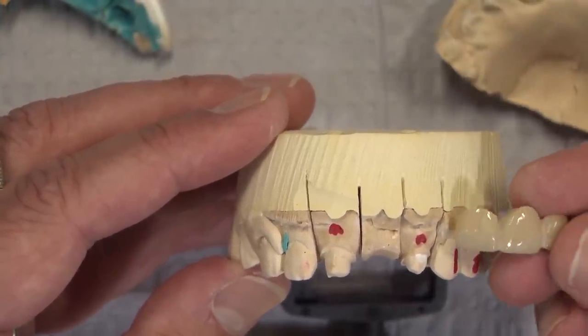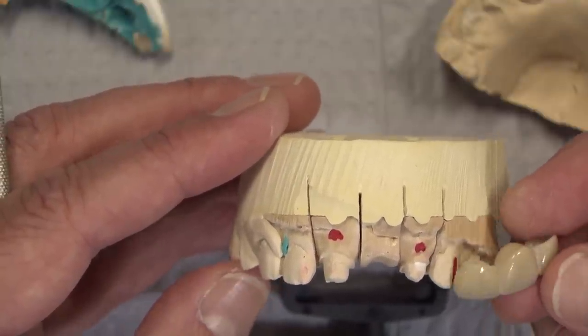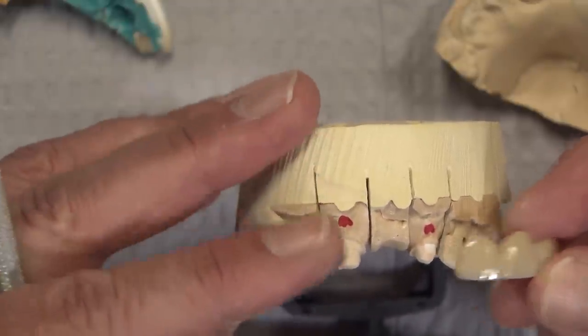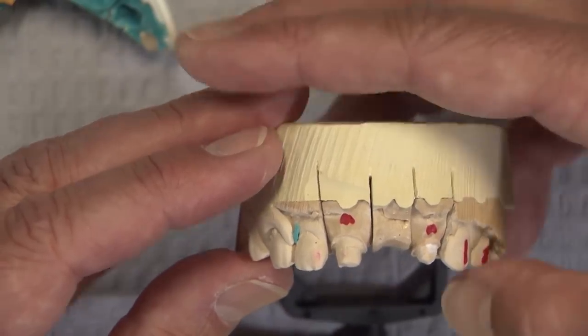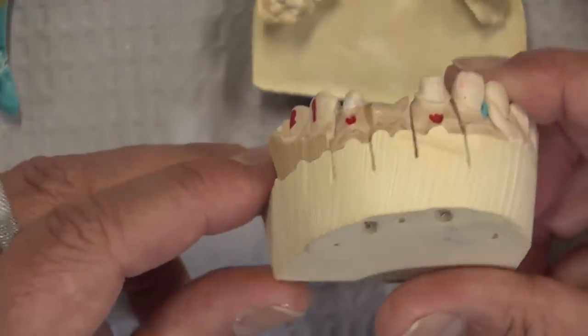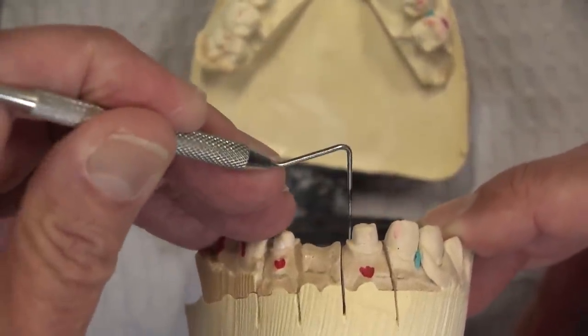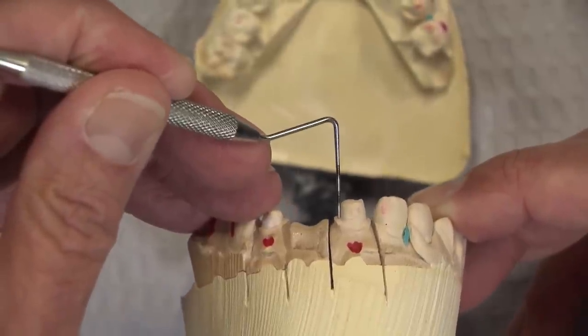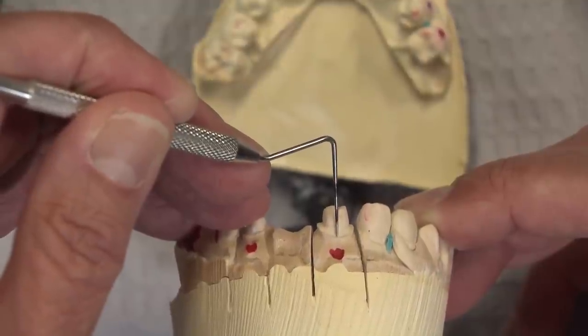We always look at retention. There are a couple things going on here: zirconia is more difficult to get a good bond to than a traditional subtractive ceramic like emax — zirconia is a little trickier. But we also just have to look at the prep length itself. We talk about short preps versus long preps; usually four millimeters is what we use as a cutoff for making that determination. And it looks like we have four millimeters there, four millimeters there, and we definitely have four millimeters there. If we look at the lingual...